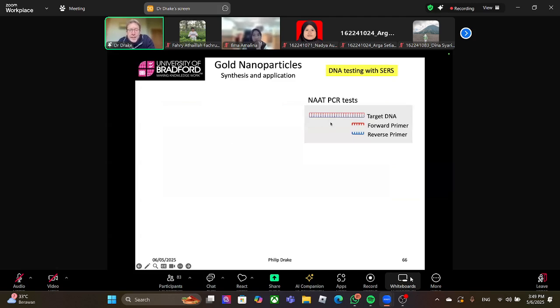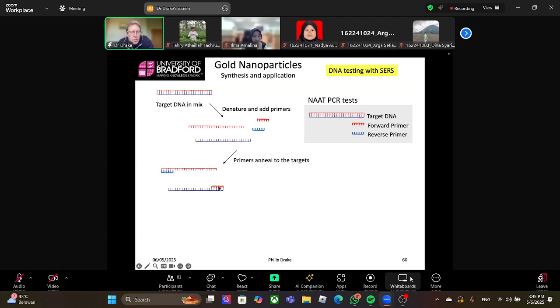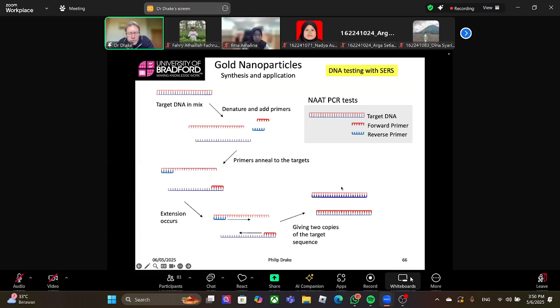You can also combine the gold nanoparticles into a DNA detection method similar to Mirkin's. So DNA is a double helix. You have a single strand, then you have the complementary strand, which forms a double helix. In PCR, you take your target DNA and denature it, so you split the two DNA strands apart into single-stranded DNA. You then add in two primers, one for each strand. The primers bind to the DNA strands. Once the primers bind, you add in a polymerase. It's an enzyme. It detects the primer and then extends and rebuilds the DNA chain. So extension occurs, and you get two double helices from one double helix. You then repeat, denature these, and go through the cycles. This is how PCR works.